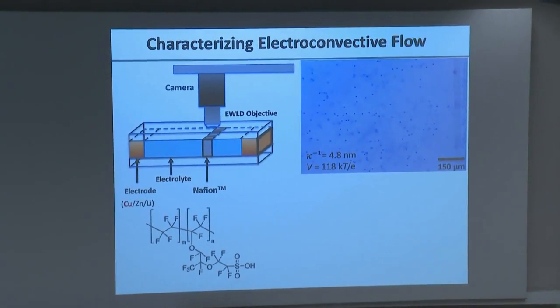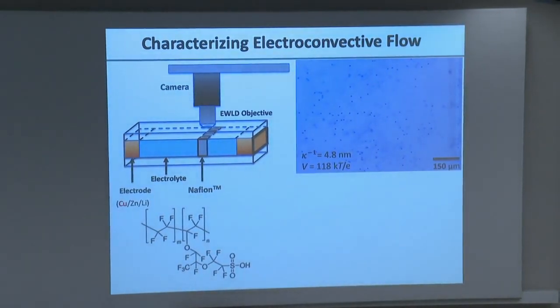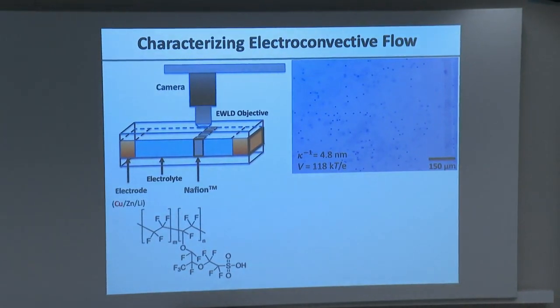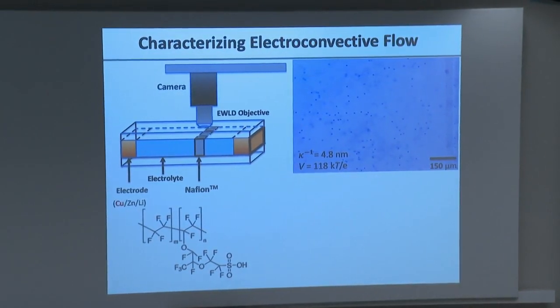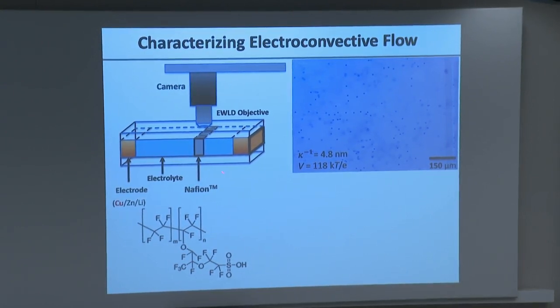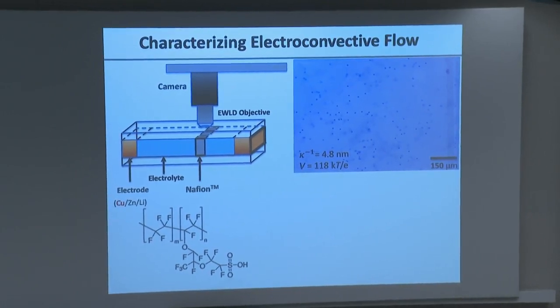So we decided, right, simulations are simulations, theories are theories. Is this really true? Okay, so we decided to do an experiment, very simple experiment, where we took an electrolyte, we put tracer particles in this electrolyte, they're dyed blue, this is why everything looks blue on the right, and we developed a microscopy cell where we can just watch and see what happens to those tracer particles, and we can then gradually ramp up the electric field to see if the simulations are right.